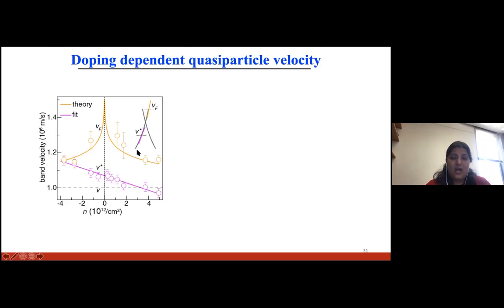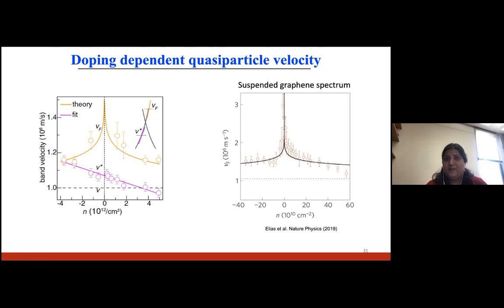And we also did a theoretical fit for our alpha value of 0.5, and this is what you see in this orange curve here. So this is a fitting. And what we see is that for our device, there is this sharpening effect towards charge neutrality, which is what you would actually expect for a suspended graphene spectrum, as was previously shown in 2019.